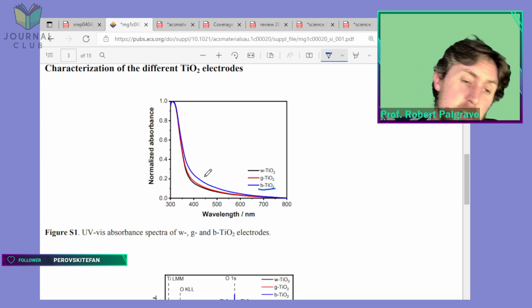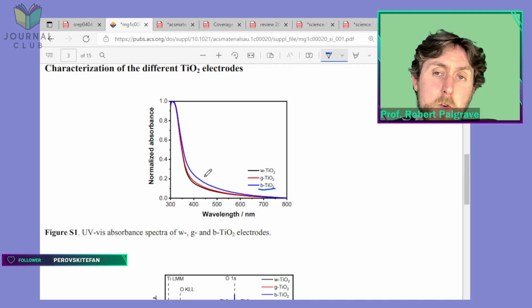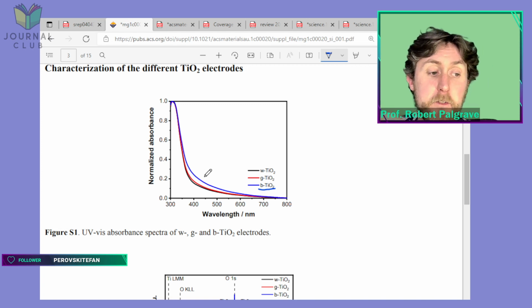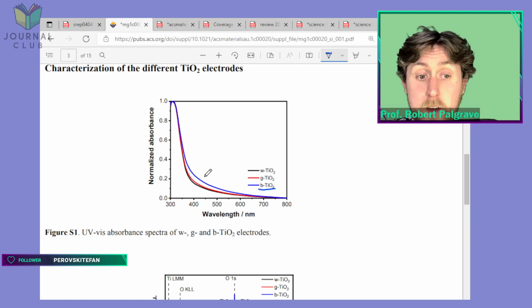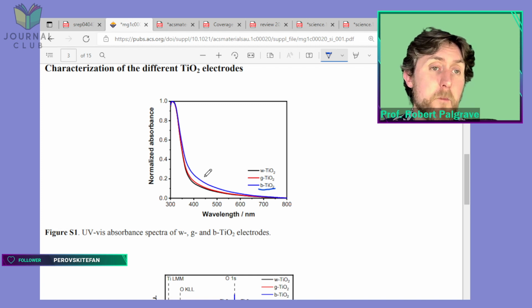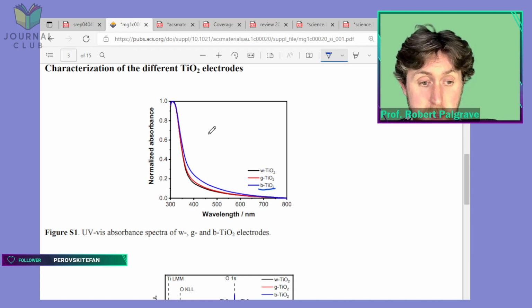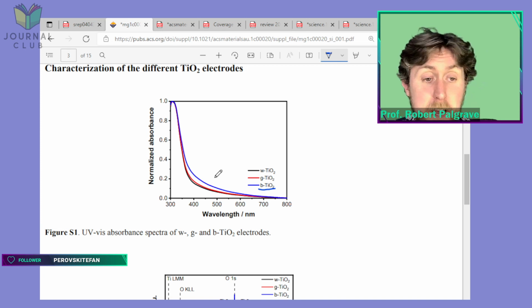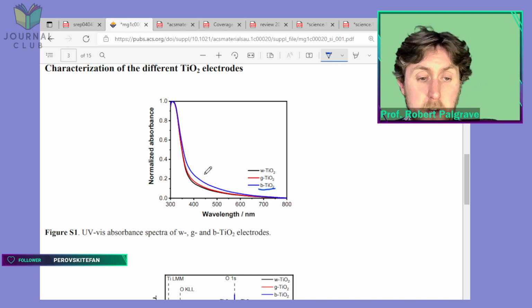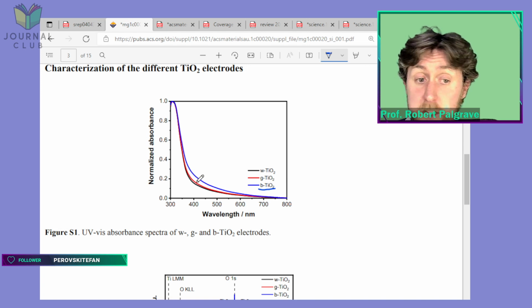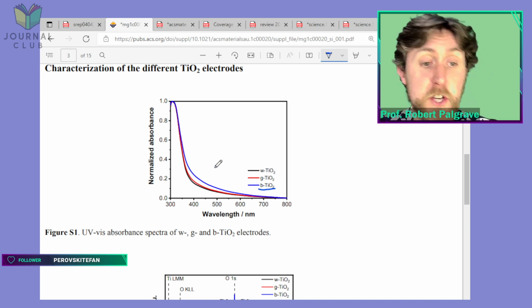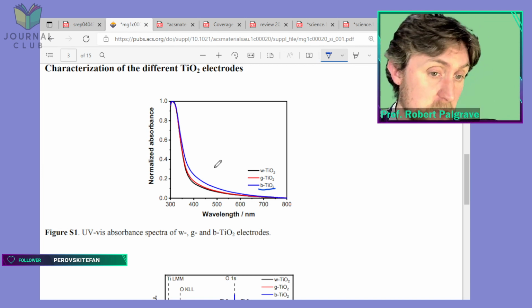You've got to think what other factors could be at play here. An important consideration is that their electrode is made of these really, really small nanoparticles. Nanoparticles scatter visible light very effectively because they're pretty much the same size as the wavelength of visible light. So the scattering of the light is going to be pretty important in the absorption spectrum they measure, depending on exactly how they measure it. So I wonder how much this change in the absorption spectrum could actually be due to a change in something to do with the nanoparticulate structure of their materials.